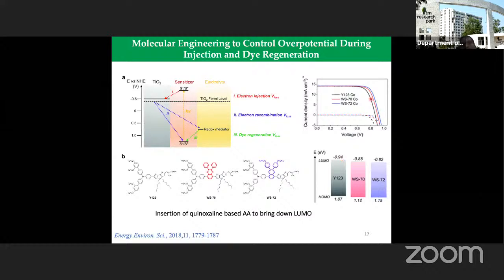You can see in this IV curve, which is here with Y123 and WS70 and WS72. WS72 gives the higher potential, higher voltage. Why? This is with iodine, I think cobalt or iodine triiodide electrolyte, I don't remember which one. But you can see this WS72 has got an alkoxy substitution. Generally, these alkoxy substitutions are very bulky. Therefore, it doesn't allow the solvent or electrolyte to come near the surface of the dye or TiO2. Therefore, the back electron transfer can be avoided.